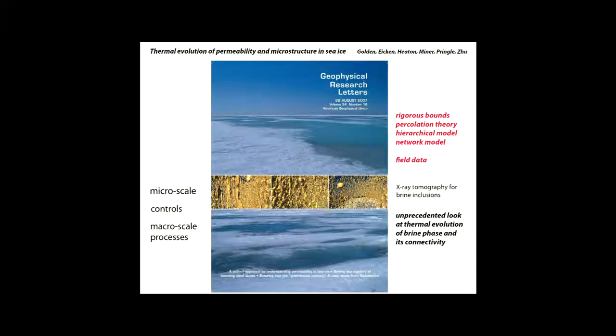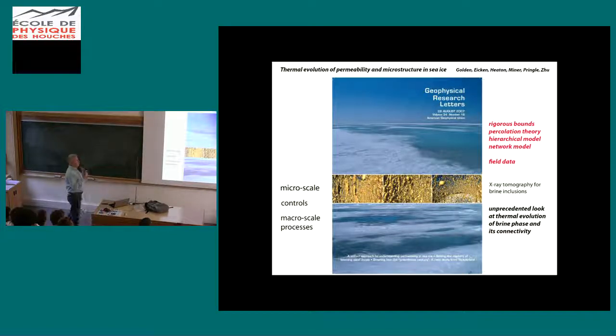Okay, so the next big step was to figure out how the fluid permeability depends on the brine volume fraction. We derived a set of rigorous bounds, percolation theory, different kinds of models, network models, hierarchical models, and comparison to field data of the fluid permeability. It was just a letter, but there was a lot of stuff in there. What we also developed was an X-ray tomography method for analyzing the brine phase in sea ice. Previously, people had taken photos and tried to reconstruct the picture, but we developed this mathematical X-ray tomography method where we could analyze all the data and do a 3-dimensional model of the brine phase. I like to view this cover as homogenization in action.